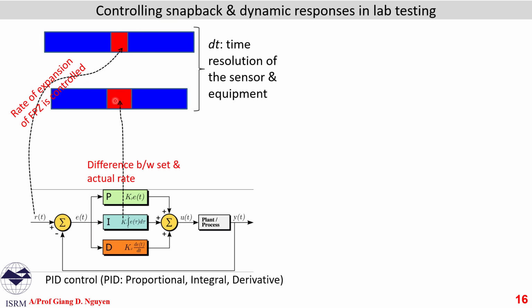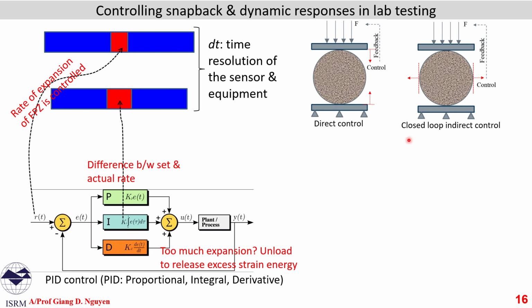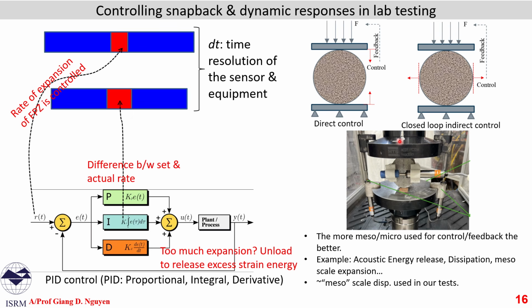And if this is expanding more than the specified one, slight unloading will happen. So this kind of loading and unloading process under PID control will gradually remove the excess strain energy and allow us to capture the whole fracture process in a very stable way. We use this in a few different kinds of tests, and one of the more challenging ones is the Brazilian disc, where we use lateral expansion from an LVDT as feedback to the control, so that the loading process, the vertical velocity here, can be adjusted gradually to remove the excess strain energy.